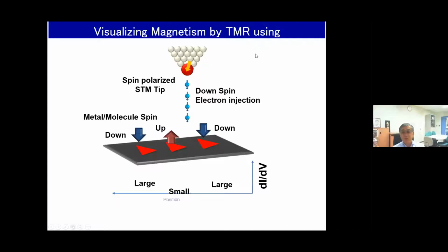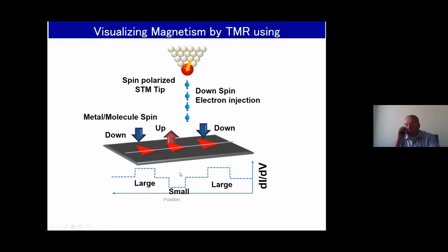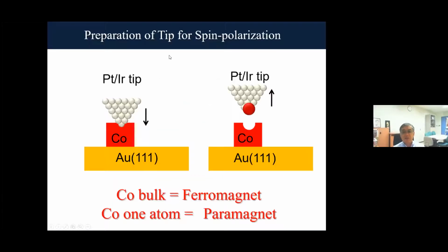So we must visualize for understanding. The spin of the tip is down, and the single molecule magnet spin is down, then high conductance. When the spin is up, the dI/dV is small, then the color is bright, dark, bright, dark. Also, we must prepare the tip for spin polarization. We usually use a platinum iridium tip. Cobalt bulk is a ferromagnet, but one cobalt atom is a paramagnet. We put one cobalt atom on the platinum iridium tip.